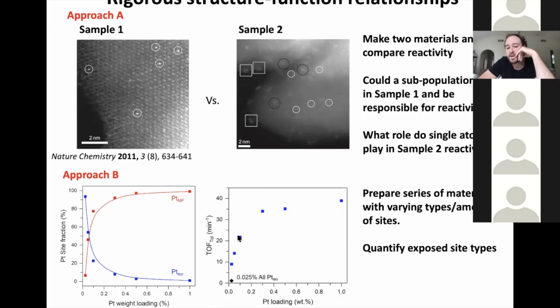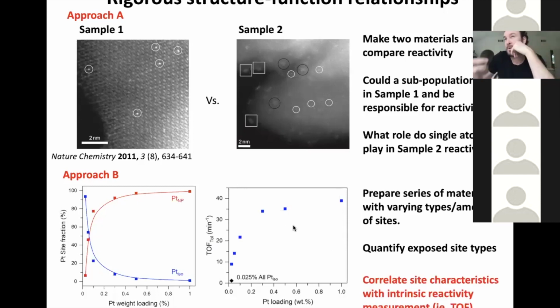And if we do have these quantitative measurements of the relative fraction of each one of these sites, then we can go make a measurement of some intrinsic property of catalytic activity, something like a turnover frequency. And we could begin to correlate these quantitatively such that we can build quantitative or rigorous structure-function relationships. And I'll show some examples of how we've been trying to do this to really convince ourselves what the behavior of these active sites is.